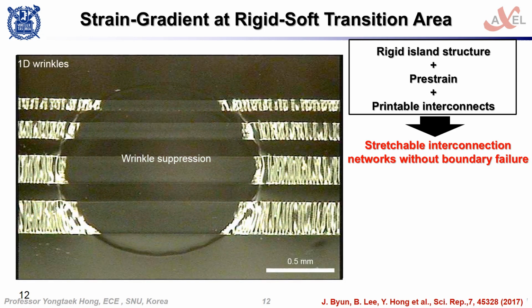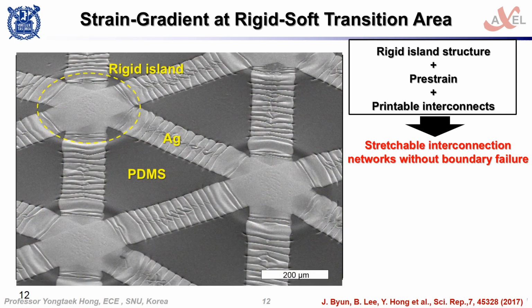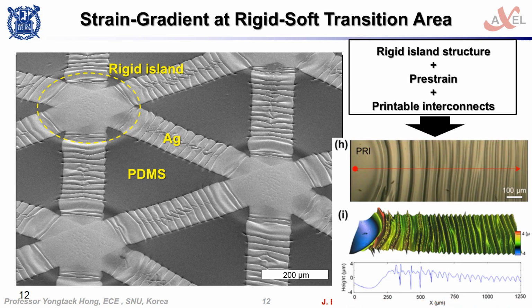In addition, pre-stretching and inkjet printing processes produce wrinkle structure with magnitude of ripples large to small from the printed rigid island. As I mentioned before, highly localized strain at the rigid and soft boundary is one of the major issues in stretchable hybrid electronics technology. This spontaneous formation of gradient wrinkle structure fully takes care of the highly localized strain at the boundary.